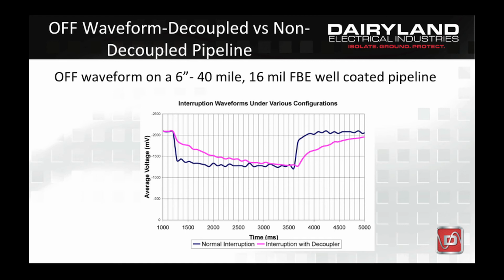This specific pipeline had multiple decouplers installed. If an off potential measurement were taken at a typical 200 to 300 millisecond measuring delay time with all decouplers installed, as illustrated by the magenta waveform, the potential measured would be significantly too electronegative relative to the potential with no decouplers installed, as represented by the black waveform.